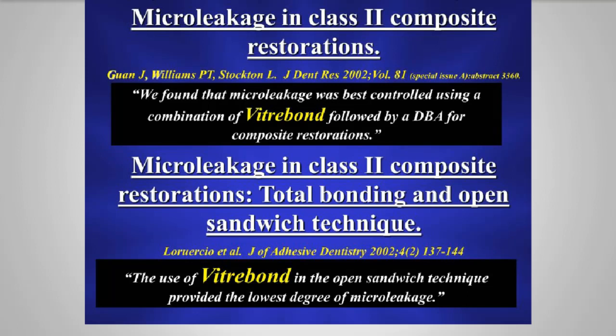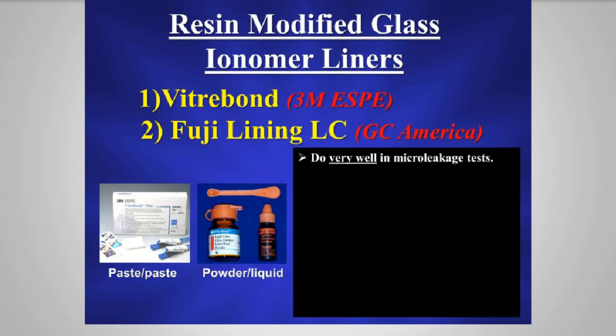And I'm really talking about two products that fit this classification category. One is Vitrebond from 3M, and the other is Fuji Lining LC from GC America. Both of these products do very, very well in micro-leakage tests. They bond very well to dentin without using a separate dentin bonding agent. It's a very good bond to composite on the other side. They have high fluoride release, and because they have high fluoride release, they're antimicrobial. There's a good long-term track record with these materials. They've been around for quite some time now. I think Vitrebond was introduced about 1990. Coefficient of thermal expansion and contraction similar to that of dentin.